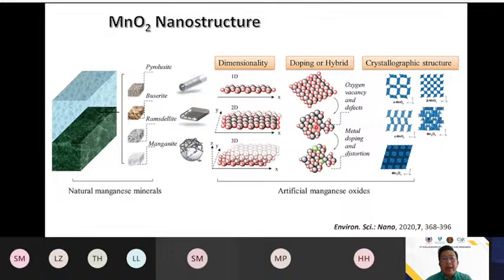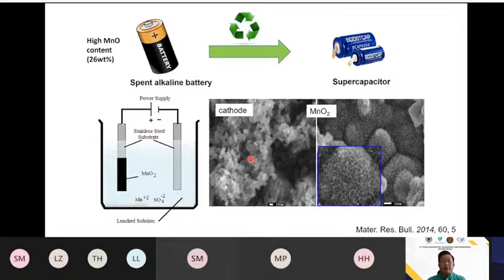First, we start off with the manganese oxide nanostructure. You can synthesize the manganese oxide in different dimensions, including 3-dimensional structures. So we started to think about where we can get this manganese source. Then we started to look at waste material, and we studied it.